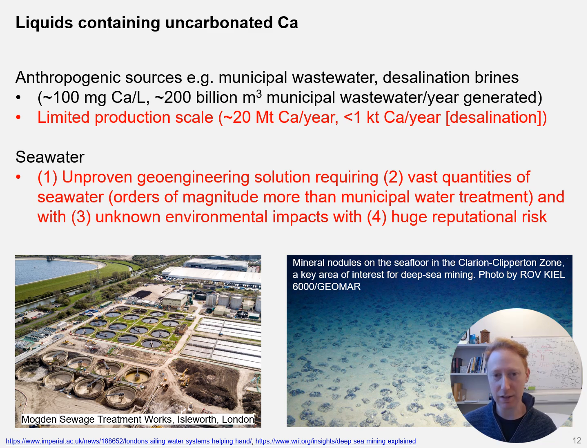Taking municipal wastewater, since it is generated in huge volumes around the world in locations where we would want to produce concrete, we produce about 200 billion meters cubed per year, and its calcium content is about 100 milligrams of calcium per litre. Now, if we do a back of the envelope calculation, we can see that there is relatively limited production scale of calcium from these resources, just because the calcium content in them is so low. So for municipal wastewater, about 20 megatons per year can be generated of calcium, and less than 1 kiloton of calcium per year can be generated from desalination brines. These numbers are multiple orders of magnitude smaller than the gigaton scale of cement and concrete materials production and the CO₂ emissions. So these liquid sources are not really relevant in terms of the scale that we're looking at here for CO₂ mineralization in concrete materials.